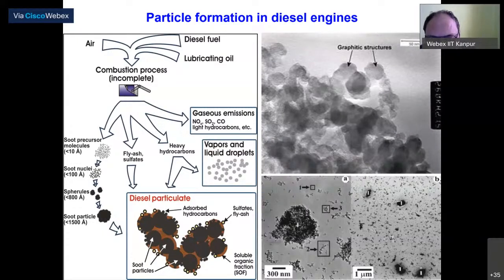And the reason why we have pollutant formation is because we do not allow this chemical reaction to complete. We literally freeze the kinetics at some point. So there are pockets inside the engine combustion zone where lack of oxygen leads to formation of either volatile organic gases or maybe soot, which we call particulate formation. Of these, particulate formation has been of interest largely because of the complex nature in which it is formed. There have been both theoretical as well as experimental studies. People have now literally looked inside the engine. Optical engines are there in the research area where they try to look at the emissions by using different parametric investigations and the kinds of fuels which might be there.